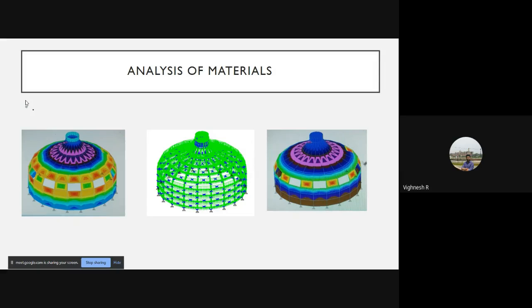One more thing we need to note here is that, analytically speaking, this structure was subjected to the temperature loading directly. There was no insulation in the first layer or third layer. It was subjected to temperature loading directly, so it was the worst-case scenario, and the results were not bad at all. We decided that we don't require any reinforcement for these structures. That was the first one.